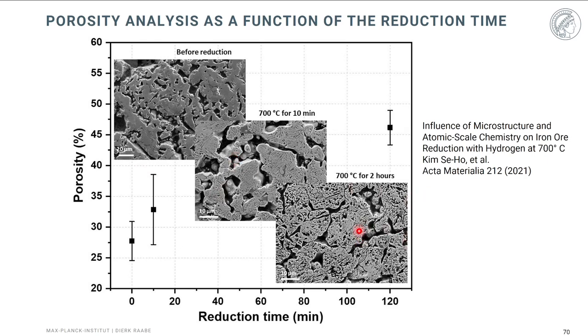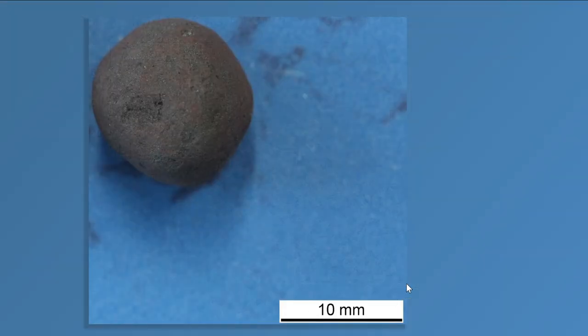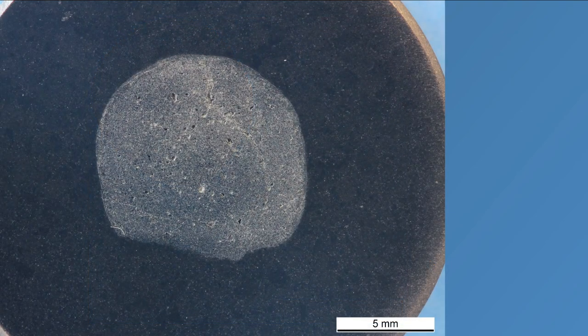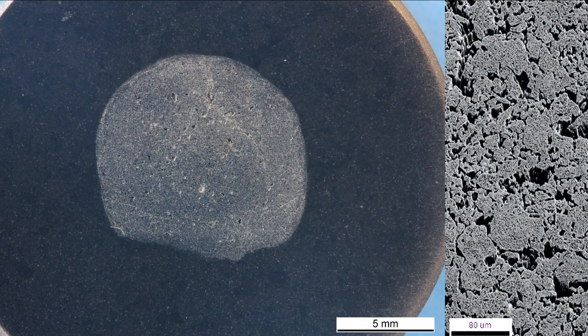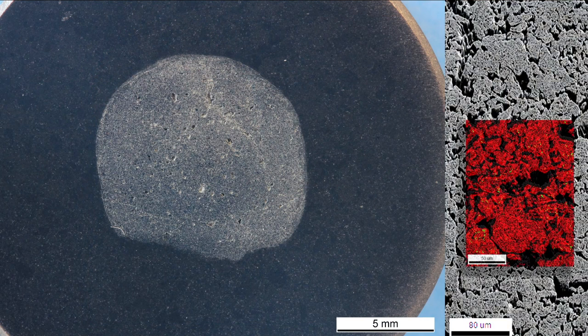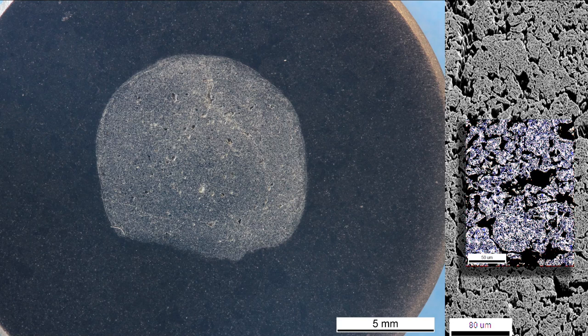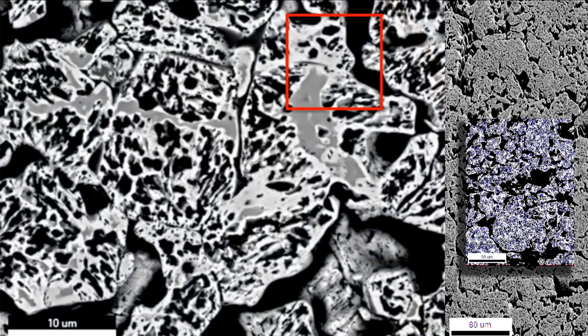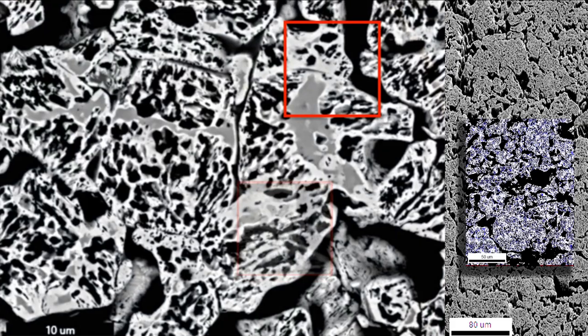After 2 hours, you can see that the material consists of a very complicated microstructure with dislocations, grain boundaries, pores, and cracks. Now, if we walk through such a commercial pellet, this little oxide piece that is an agglomerate of fine ores is called a pellet, and it's typically used in direct reduction. When you cut it open, you can subject it to all kinds of microscopy mapping techniques, be it chemical or structural. You can look at the phase, at the distribution of the grain boundaries, and so on. So the same things that you would do in ordinary materials, and then you get these very complex microstructures revealed.